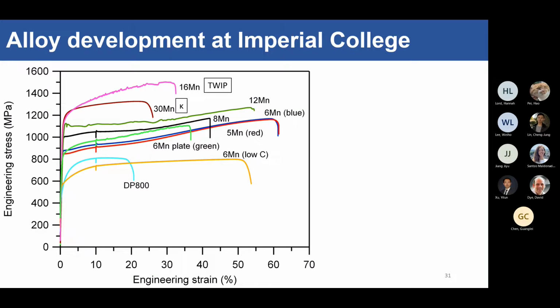All right, so now let's tie it all back. So this is our alloy development at Imperial College. We've worked on many, many different manganese-containing steels. So this is the high manganese-containing steel. This is your 16 manganese TWIP steel, and your 30 manganese, this is your kappa carbide strengthened steel. So you can see that they're very, very strong, and also with quite a bit of ductility as well. So as we decrease in manganese, very sadly, you can see the strength starts to go down as well. And that's a consequence of losing some of your solid solution hardening as well.